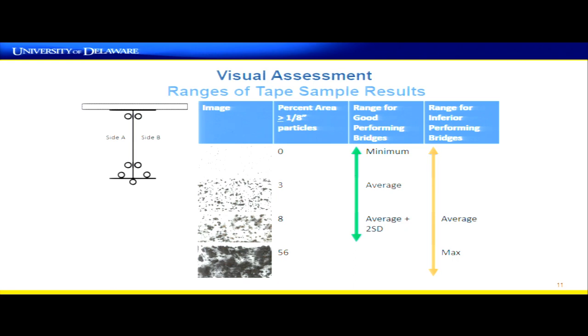So in a good performing bridge, you might get a range of these tape samples where you have just a few tiny dots. This might not even be corrosion particles. It's possible this is just dust. Mostly it's going to look like this as the average. And maybe on the higher end you see some where about 8% of the space is occupied with these larger particles. For an inferior performing bridge, you have a case that looks as bad as this in some cases. So it's pretty clear when you look at it from this perspective which bridges are performing well and which ones have some active corrosion.